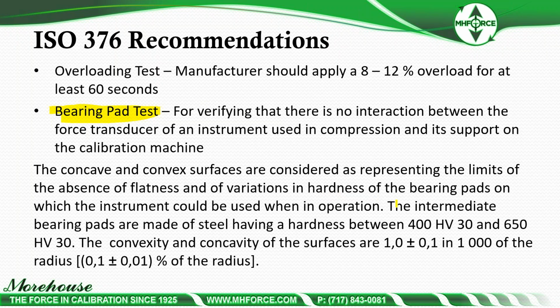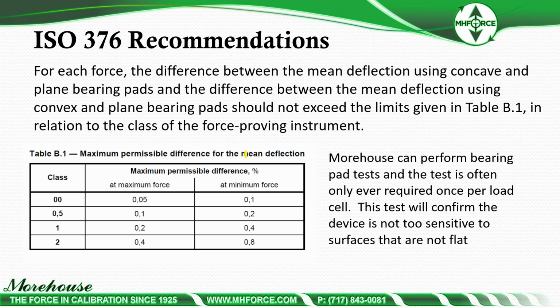The intermediate bearing pads are made of steel having a hardness between 400 HV30 and 650 HV30. The convexity and concavity of the surfaces are 1 plus or minus 0.1 in 1,000 and a radius of 0.1 plus or minus 0.01% of the radius. So for each force, the difference between the mean deflection using concave and plane bearing pads and the difference between the mean deflection using convex and plane bearing pads should not exceed the limits given in table B1 in relation to the class of the force proving instrument, which is very interesting.